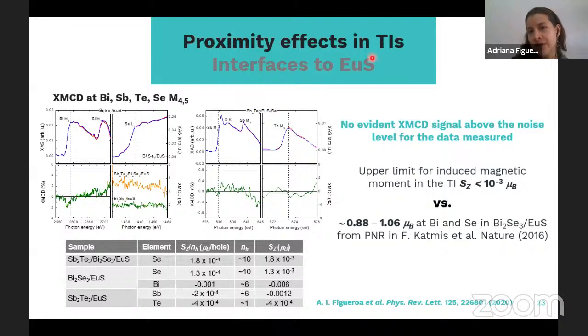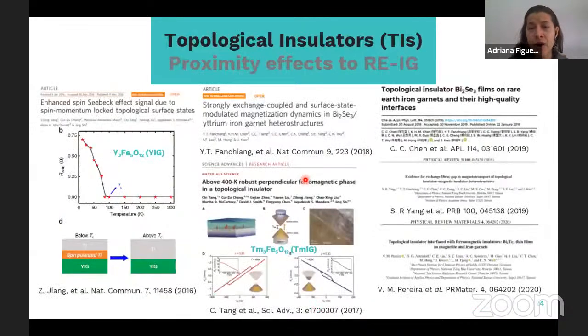And then, well, this is in terms of europium sulfide. So we studied these effects with other magnetic insulators. In this case, we used rare earth iron garnets, for example, yttrium iron garnet or thulium iron garnet, which are also magnetic insulators that have been used in interfaces with the TIs to study these proximity effects. And there have also been reports of polarization of spins within the TI at the interfaces with these iron garnets, with these magnetic insulators.